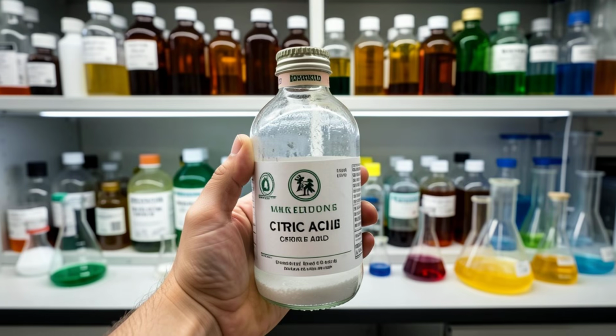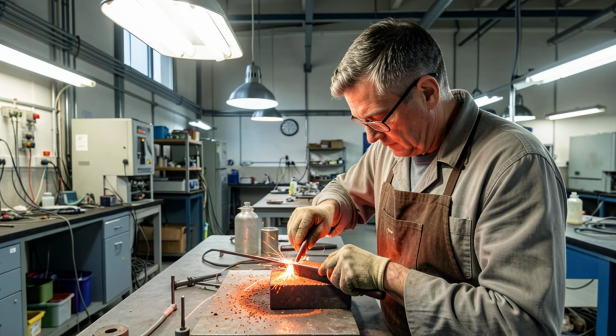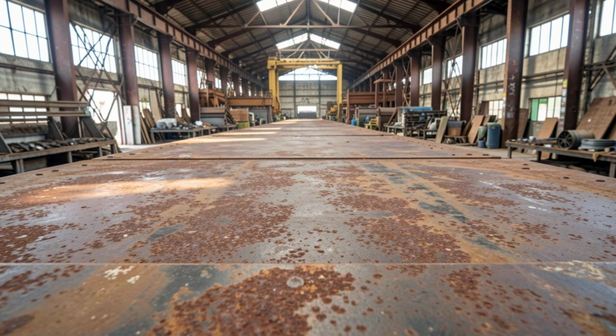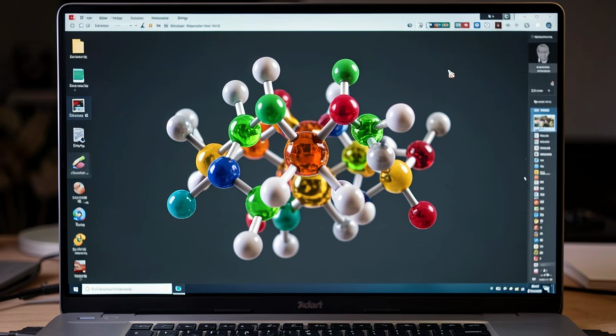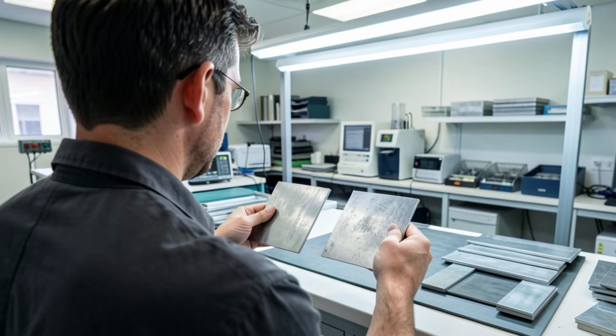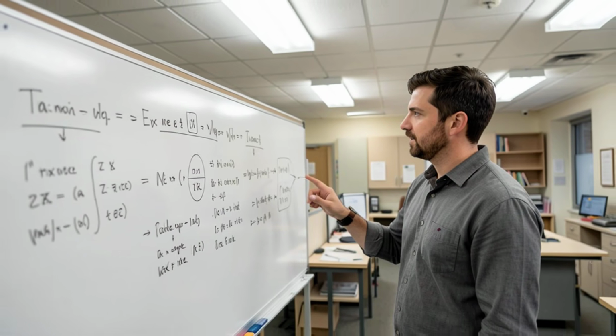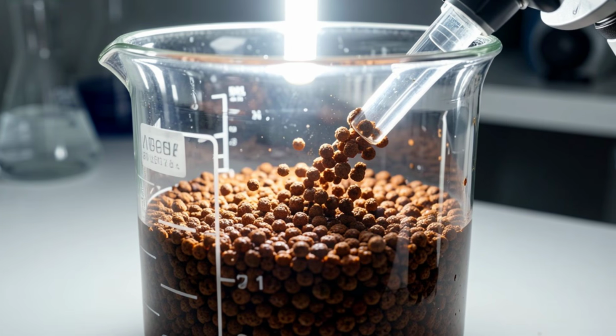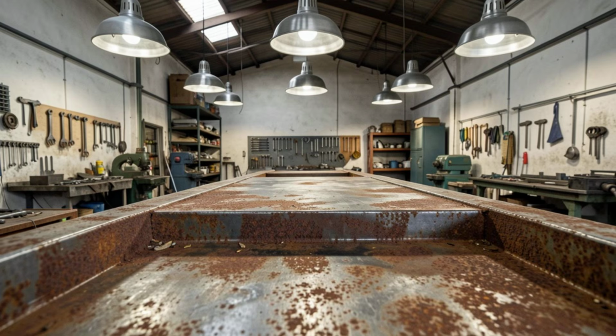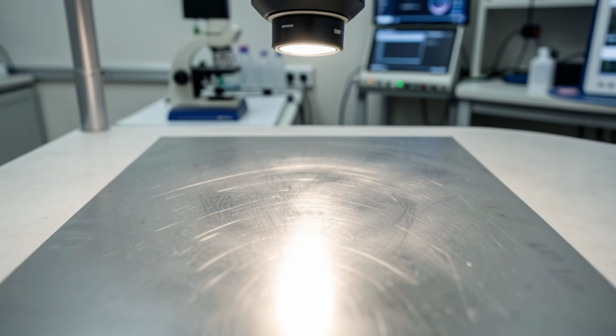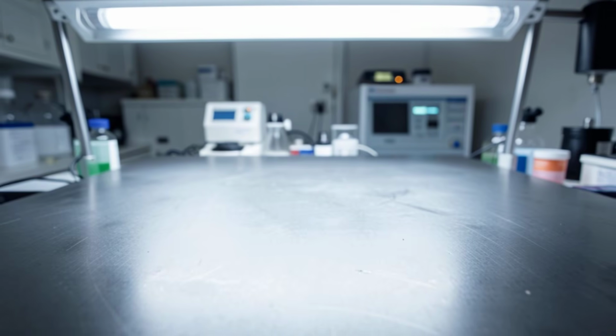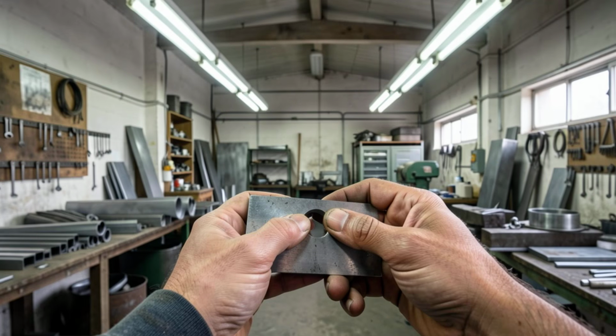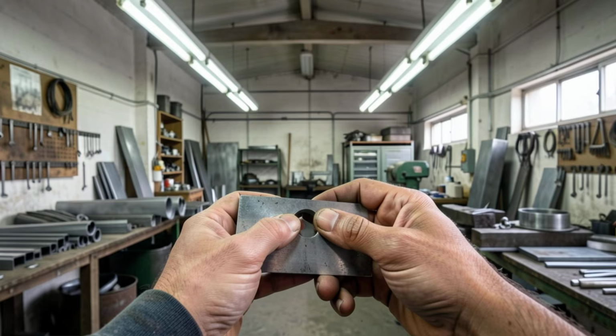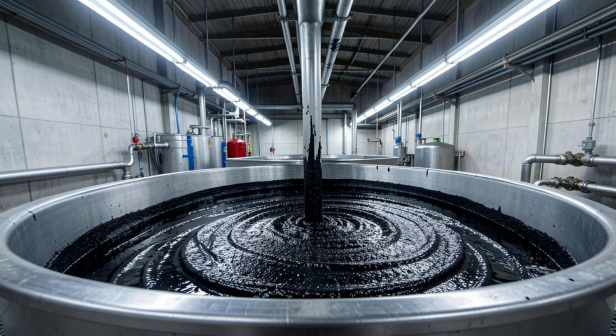The key word there is selective. Citric acid, in the concentration range we are working with, targets ferric iron, the oxidized iron in rust, with a much higher affinity than it targets the iron in non-oxidized base steel. That selectivity is the entire reason this method works without damaging the parent metal. The rust molecules are pulled into solution. The healthy metal underneath is left intact and flat. No abrasion, no etching, no indiscriminate acid attack on the surface you are trying to preserve.